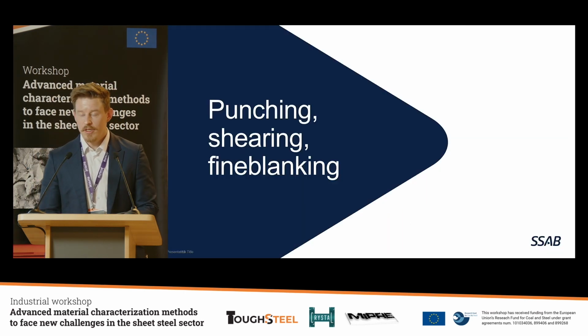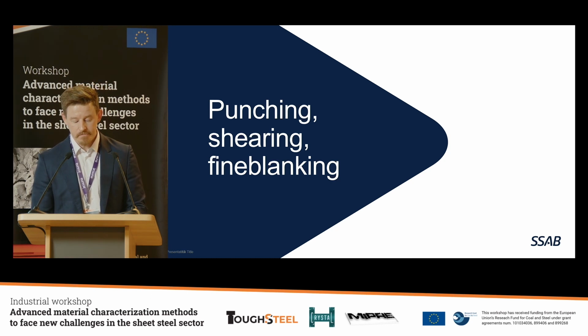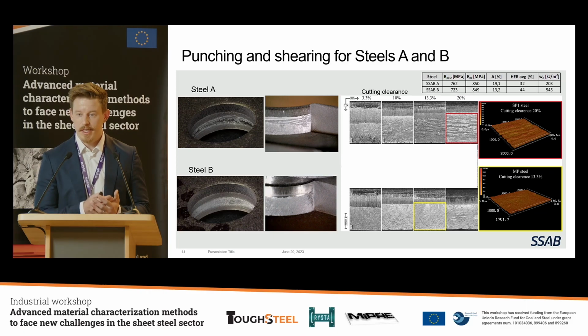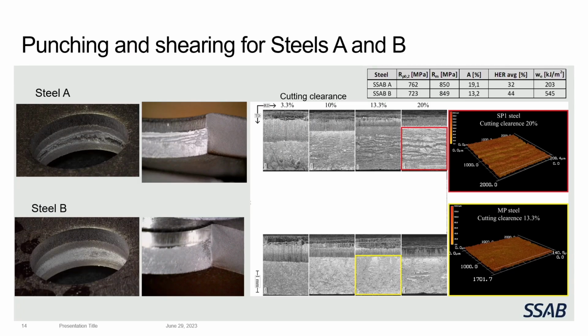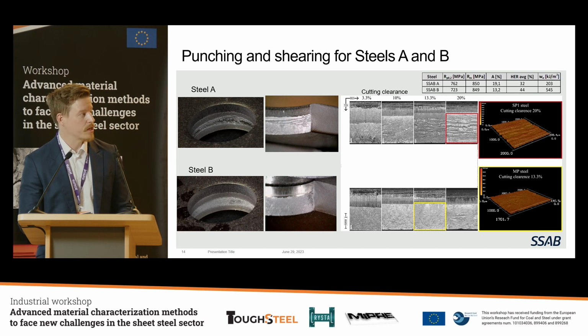Then some results on punching, shearing, and fine blanking. We selected 2 materials, steel A and steel B. As you can see, really identical mechanical properties when it comes to strength, rather similar hole expansion ratios, but now we have 2 different levels of essential work of fracture. And steel A, punched hole, you can see the surface is not really nice. And we have also the shearing results with the different cutting clearances here. You can see that the fracture surface is not looking really nice after cutting. But steel B is showing almost perfect cut edge in all these cases. It's not sensitive to the cutting clearance, for example.